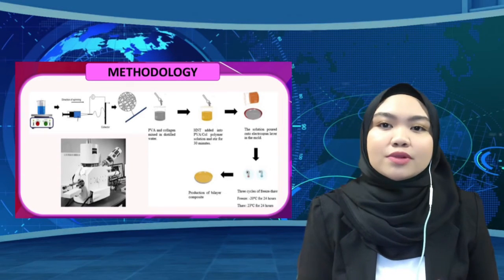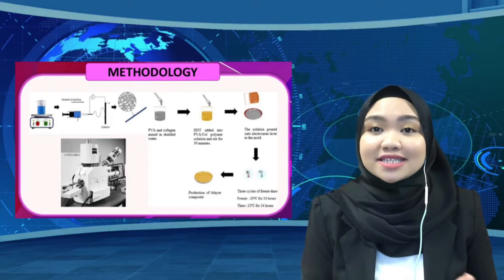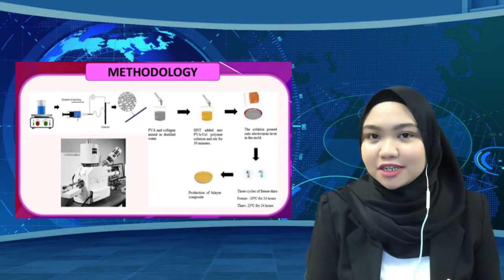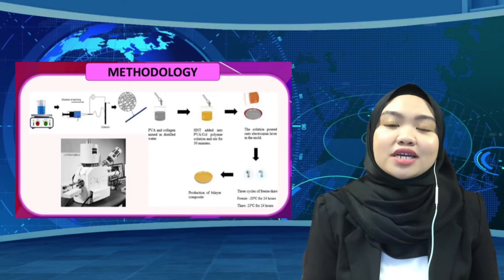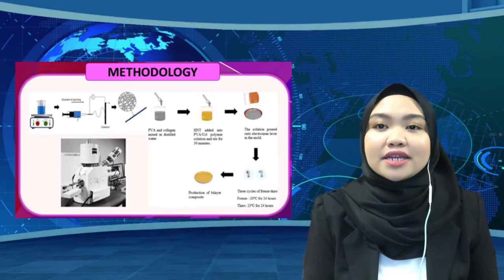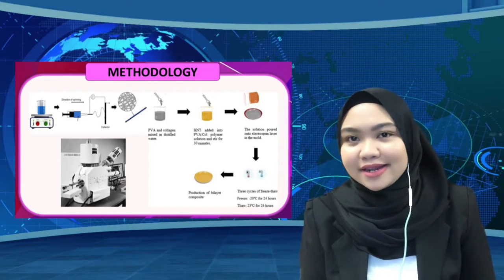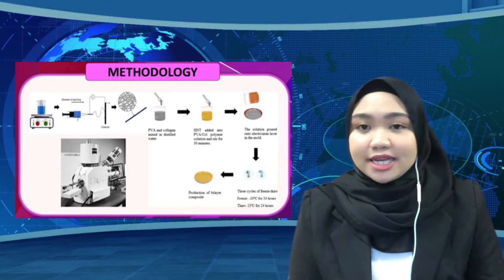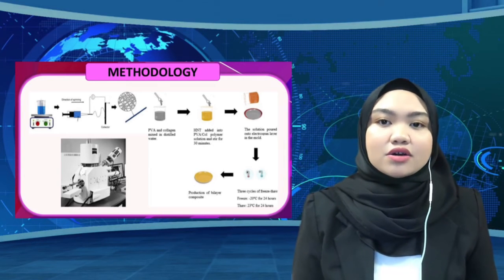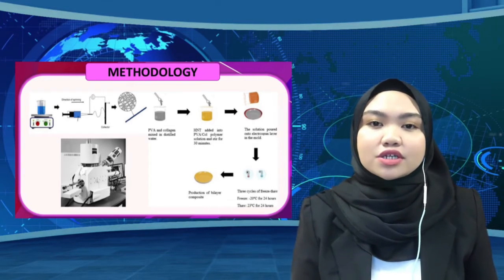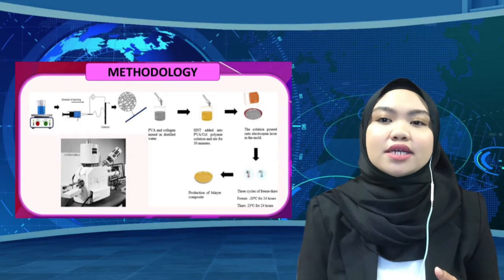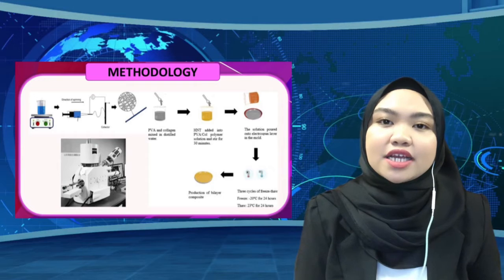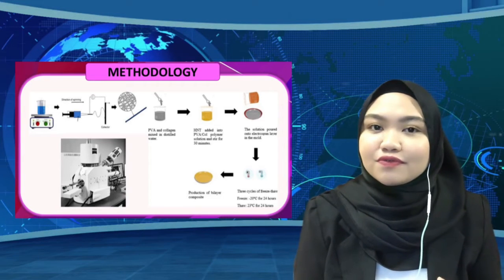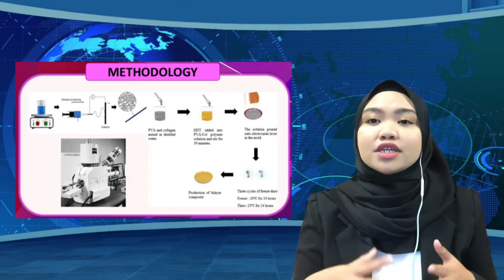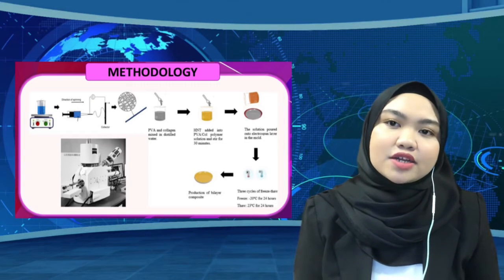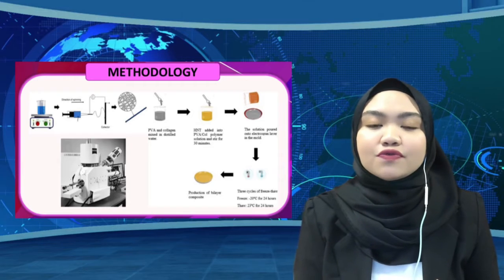The copolymer fluid will be injected into a 5 ml disposable plastic syringe using a 20 gauge needle. The syringe will be loaded into an electrospinning unit with a horizontal setup that delivers the polymer to a collector panel. So next is the preparation of the bilayer composite. PVA and collagen will be mixed at a PVA to collagen ratio of 90:10 in distilled water at 90 Celsius, forming a 50% concentration solution. Then 5% of HNT will be added into the PVA collagen polymer solution by stirring for 30 minutes until the composite solution is fully homogenized.